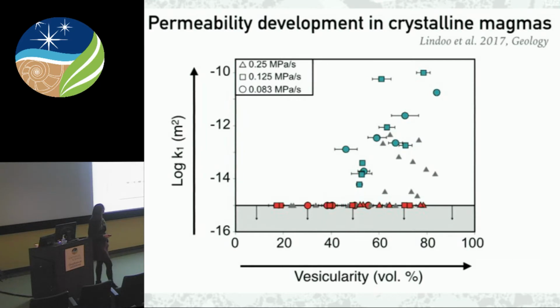What was super exciting was that these samples were actually permeable, and we see that they become permeable around 50 volume percent. Before I get ahead of myself, the gray triangles are the silicic experiments from the previous study, and the red symbols are impermeable basaltic andesite experiments, and the blue are permeable.